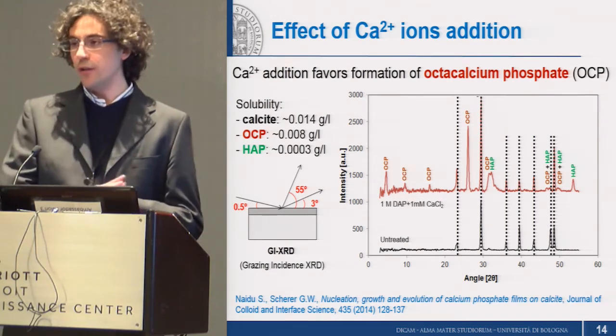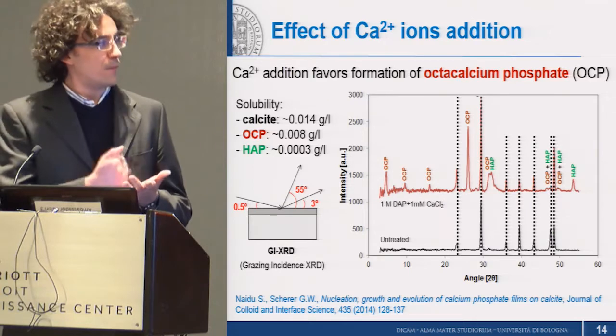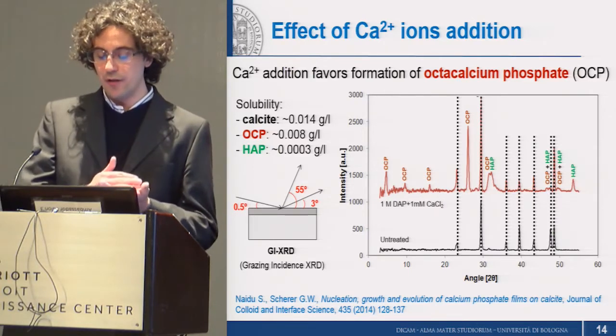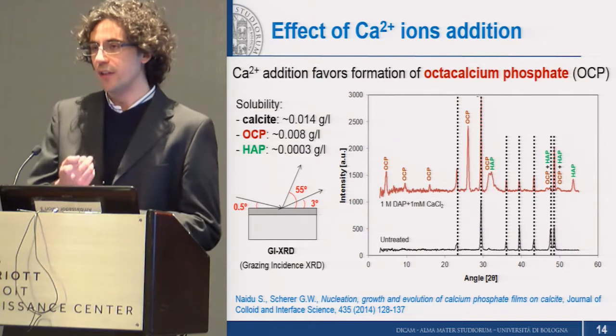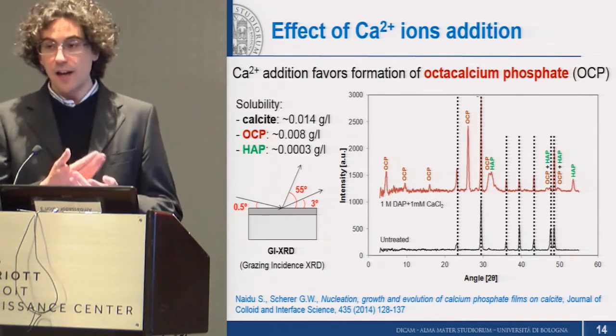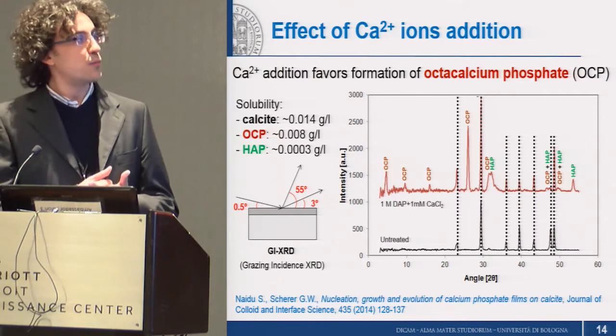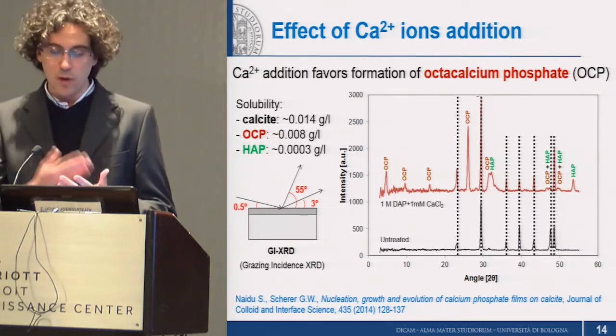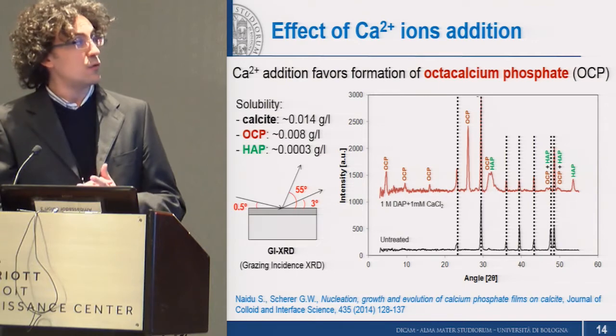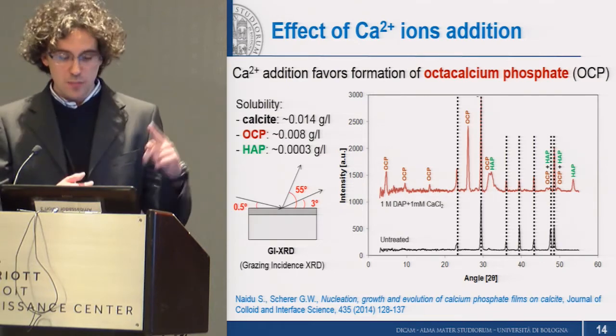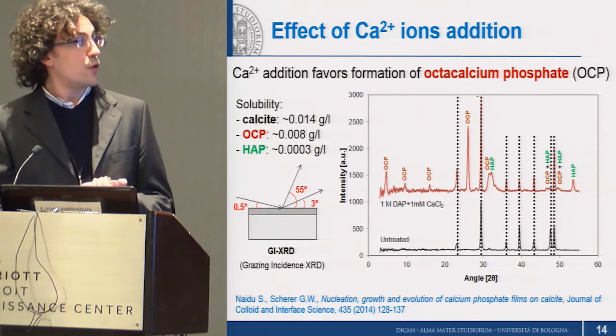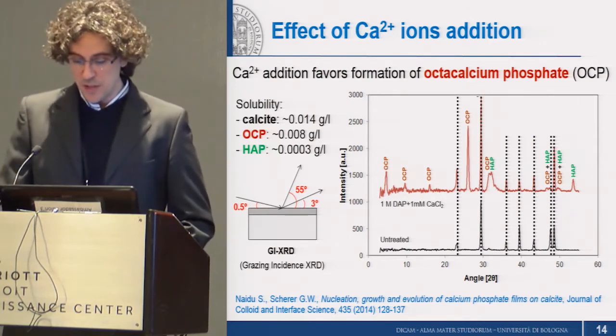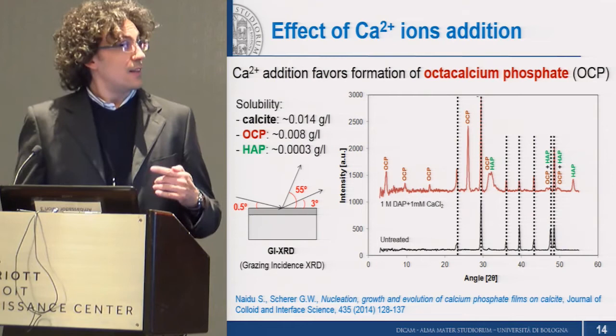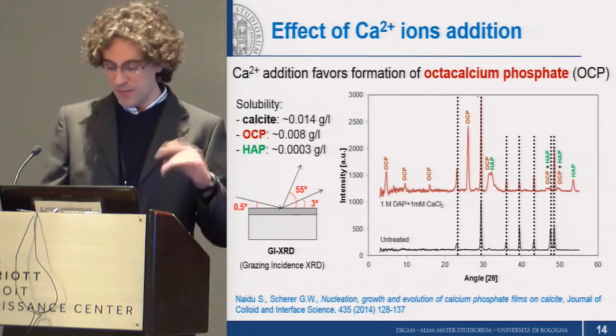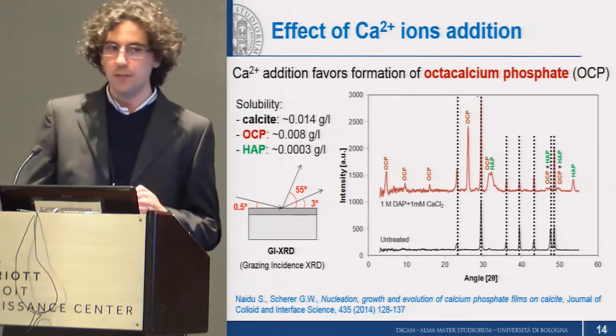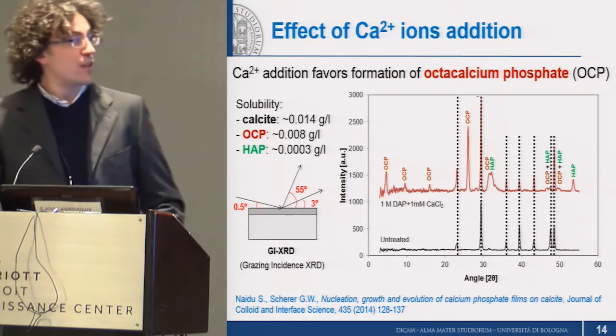This is very important because HAP was identified as a very promising mineral because of its very low solubility. In case calcium phosphate phases form which have a higher solubility, this could be a serious problem in our case. So we found that when we add calcium ions to the solution, we form both HAP, hydroxyapatite, and octacalcium phosphate, which is a different mineral, of course. As you can see, it has a higher solubility than HAP, but still a lower solubility than calcite, so it's still positive for our aim of protecting marble.